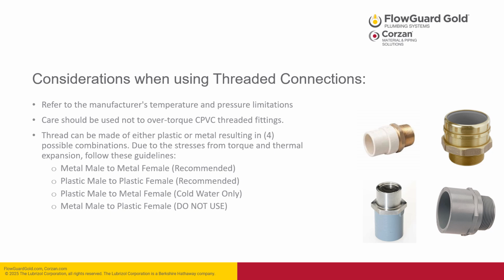When using threaded connections with FlowGuard Gold and Corzan, always refer to the manufacturer's temperature and pressure limitations. Take care not to over-torque CPVC threaded fittings. The thread can be made of either plastic or metal, resulting in 4 possible combinations. However, due to the stresses from torque and thermal expansion, make sure to follow these guidelines. You can use a metal male to metal female thread or a plastic male to plastic female thread under all conditions. However, plastic male to metal female should only be used in cold water applications, and you should never use a metal male to plastic female connection.